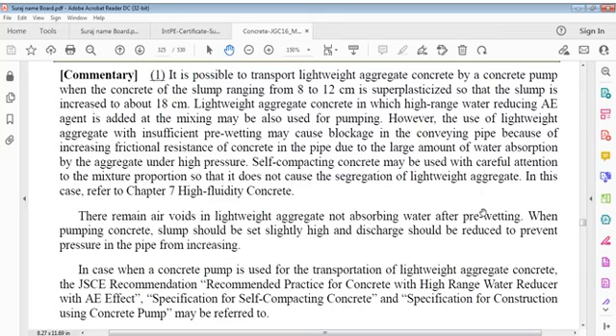However, use of lightweight aggregate with insufficient pre-wetting may cause blockage in conveying pipe because of increasing frictional resistance of concrete in pipe due to large amount of water absorption by aggregate under high pressure.